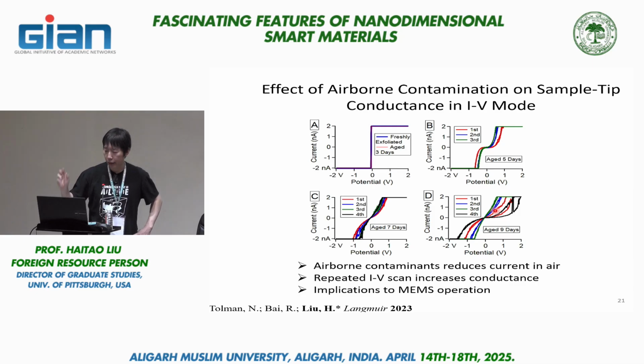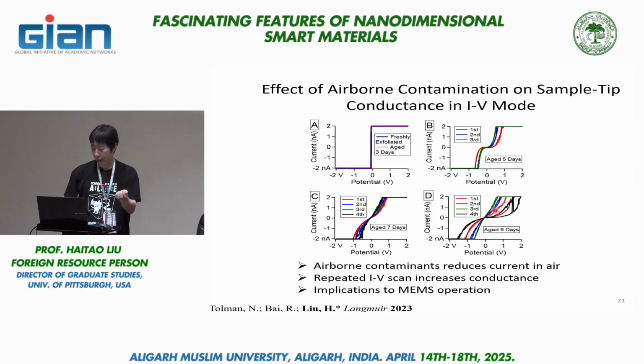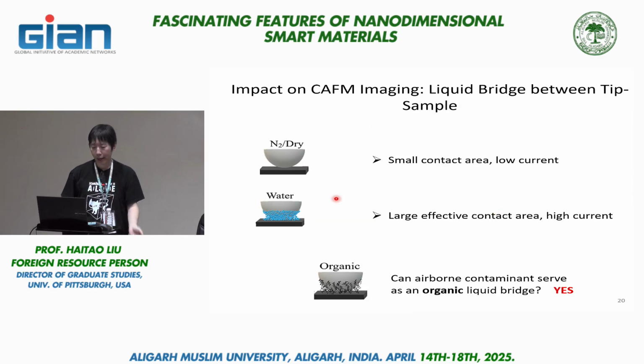Okay. We also did experiments which I didn't show here. We look at the conductivity in a dry and clean environment versus a dry and dirty environment, and then a wet and clean environment and a wet and dirty environment. And we were able to show that in this case, you get the least electrical conductance, because there's no meniscus established between the tip and the substrate. And in both those other cases, you can see an enhancement in the electrical conductance, okay, compared to this one.